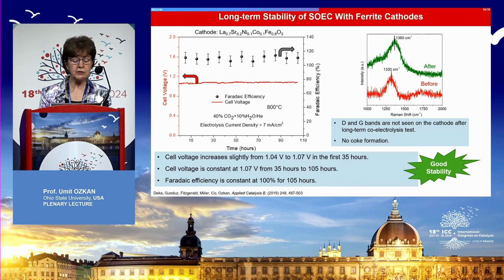And one final slide on the CO2 case, and when we kept this cell online for 100 hours, it was very stable. You can see the cell voltage here, Faraday efficiency right around 100%. And then we also looked at post-mortem characterization, and the sample really did not show any coking on the surface. We didn't really see the D or G bands. So there's very good stability.